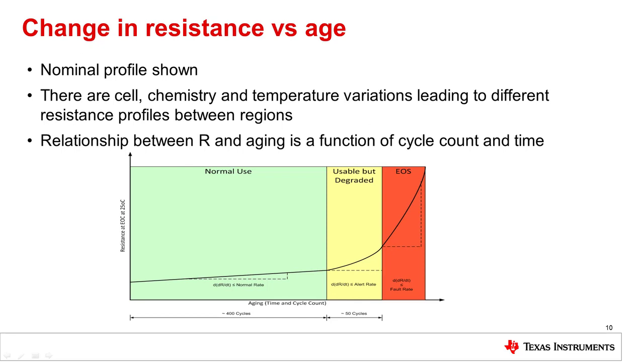The algorithm uses these learning pulses to measure the resistance of the battery, and from that data it estimates whether the cell is approaching the end of its usable life. As a cell ages, the resistance will tend to creep up as a function of time and cycling. Over time, the resistance increases somewhat linearly in the early stages, then becomes super-linear, until finally — when approaching limited usefulness — the resistance spikes off quite heavily. This is what the algorithm in the BQ34110 is actually trying to identify.